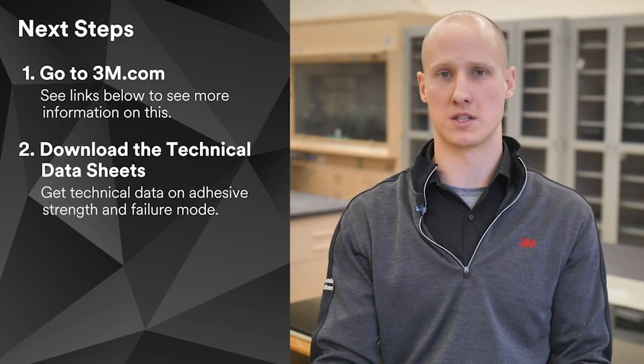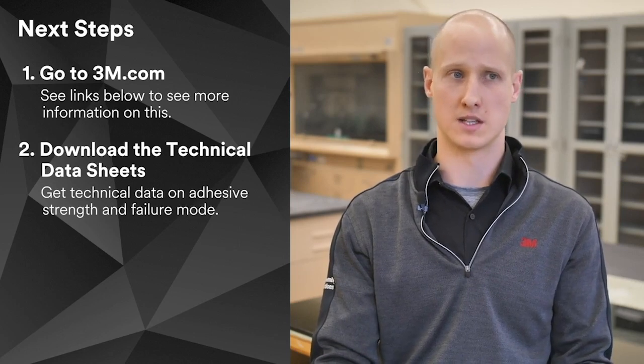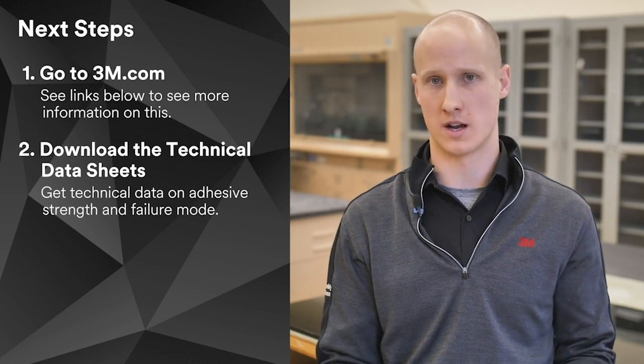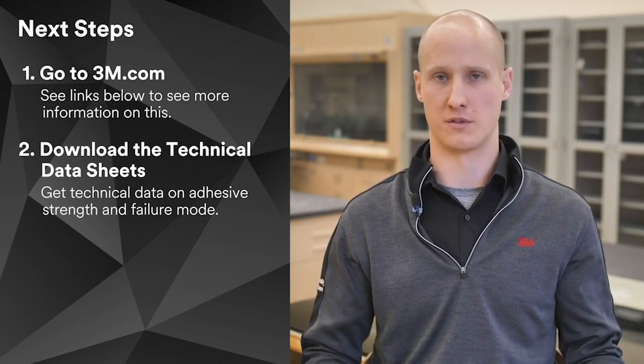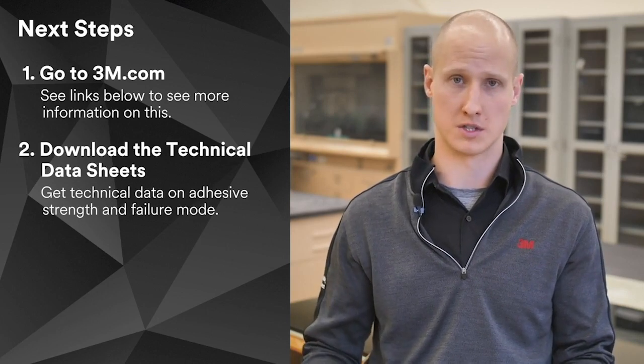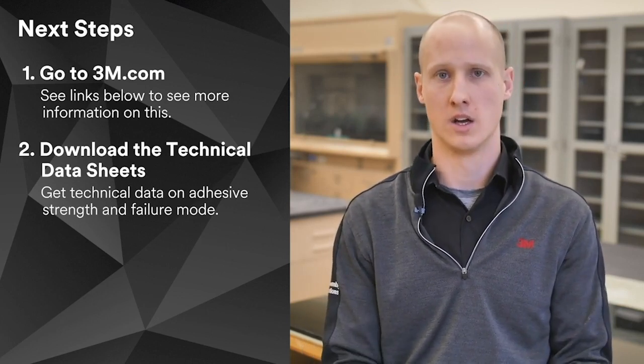But you'll also see a failure mode. So if you look at the failure mode and you see that it's cohesive failure, that means that that adhesive tested under those conditions remained bonded to both the substrates after it pulled to failure versus adhesive failure, which would indicate that it peeled cleanly from one of those substrates. So you can use that as a guide on whether it's sufficient.